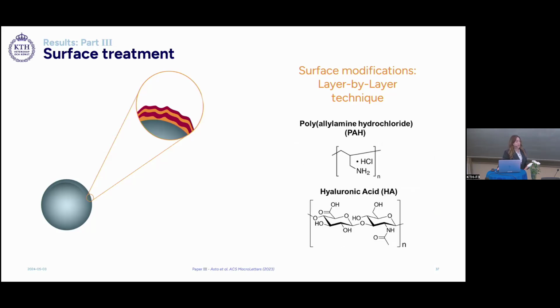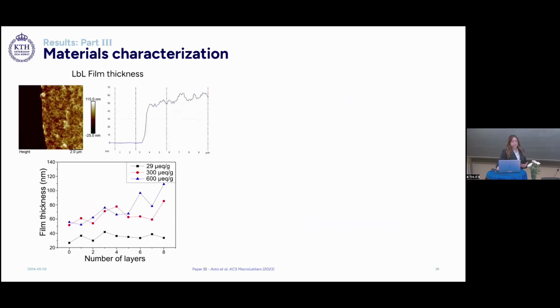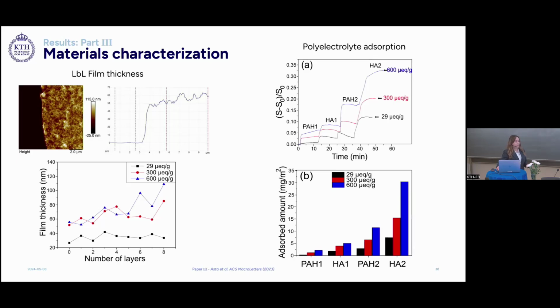For this, we used polyallylamine hydrochloride and hyaluronic acid as the polyelectrolytes, since they have been used and showed very good adhesive properties previously. And the first step is to figure out how much polymer is adsorbed on the surface of the material. And for this, we performed a scratch test using AFM to measure the thickness of the LBL film. And we used stagnation point adsorption reflectometry to measure the adsorbed amount of the polyelectrolytes on the surface. And we can see that by adsorbing more layers on the surface, the adsorbed amount increases, as well as the film thickness.